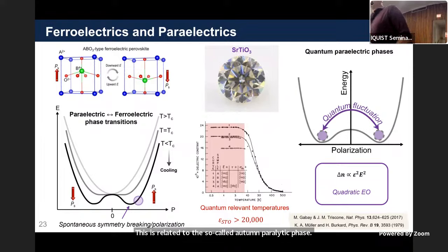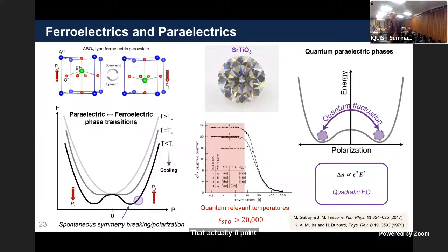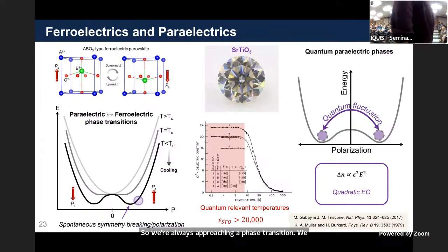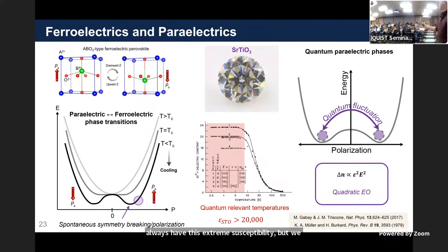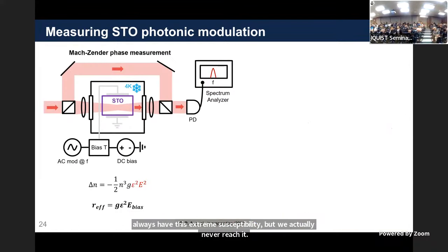And basically what that means is that this potential well is so flat and this barrier is so low that zero point fluctuations bounce you back and forth between these two polarization states. And so you actually never undergo this phase transition. So we're always approaching a phase transition. We always have this extreme susceptibility, but we actually never reach it. But that's actually great for having this high dielectric constant.